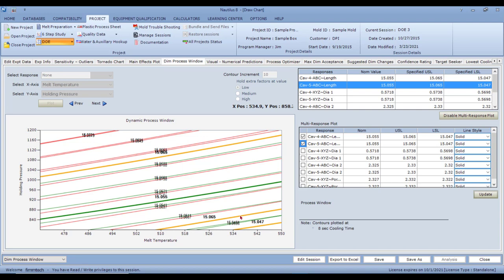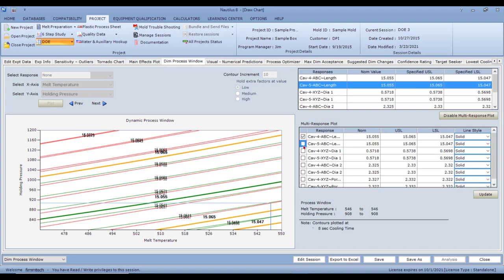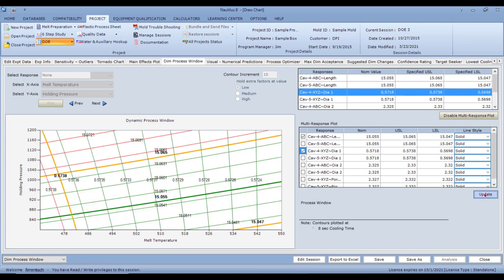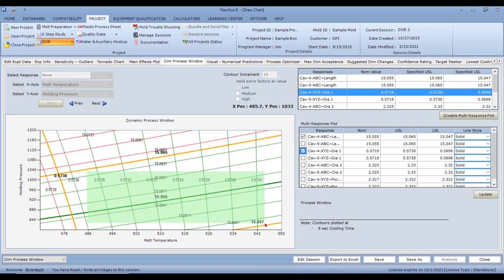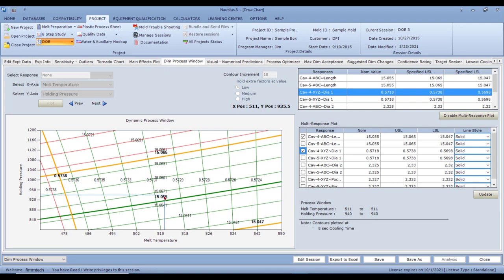This upper spec limit is for cavity 5 and the lower spec limit is for cavity 4, so you can only work in this intersection — the process window is extremely small for both cavities together. You can also combine cavity 4 length and cavity 4 diameter, update it, and see a larger intersection — the dimensional process window where all green lines intersect. You can draw that window and select the most robust area within it.